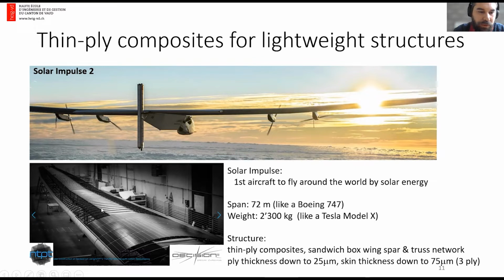For example, the main wing is made of a large wing box, a square wing box that you can see here, which is itself a sandwich panel structure. And it's not heavily loaded because of the weight of the aircraft, which is fairly low. But the design is mostly constrained by the minimum thickness of the ply that can be used for producing a balanced skin or sandwich. Based on my own estimate, in this design the skin thickness for a 3-ply layup could go down to 75 micrometer, which is thinner than a sheet of paper, but made of high strength or high modulus carbon fiber composite. So without this Thin-Ply technology, this aircraft could not fly. And that's fairly simple. So that's the first justification of why.